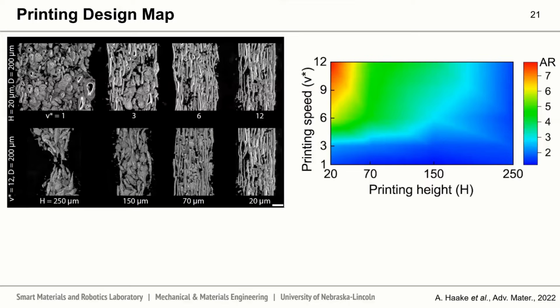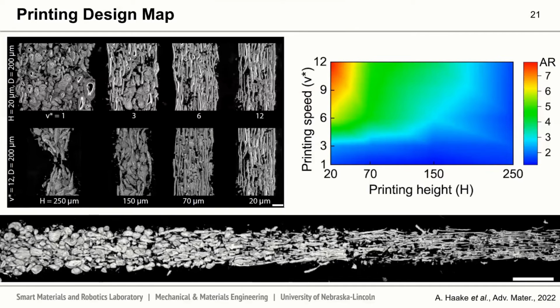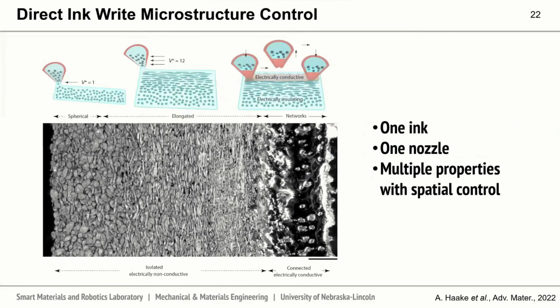With this, we are able to spatially control the microstructure throughout each filament that is printed within the structure. We see on the left hand primarily spherical microstructures, all the way to needle-like microstructures on the right, over a distance of about 13 millimeters. We're able to very quickly change the aspect ratio of these particle fillers throughout a printed part.